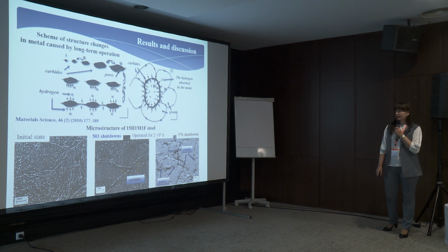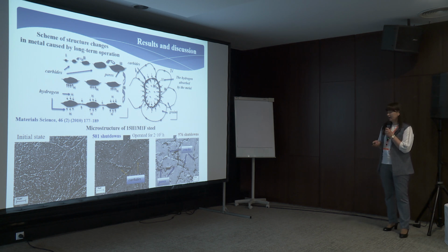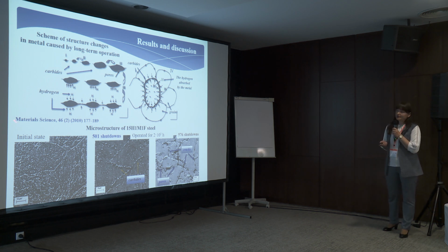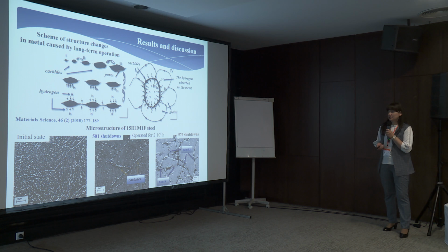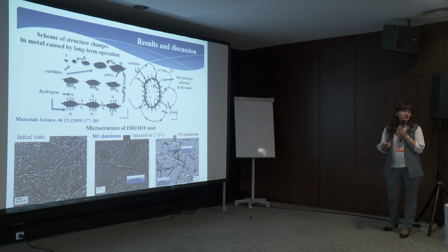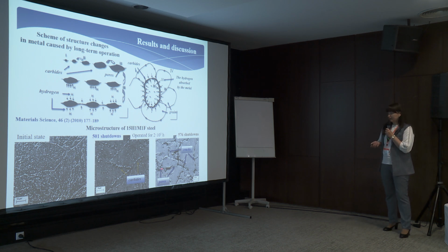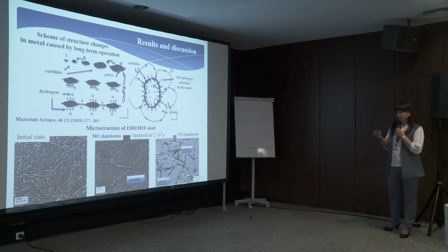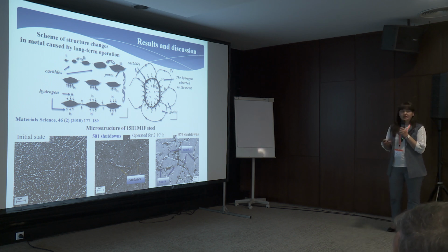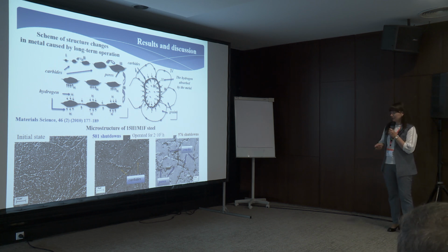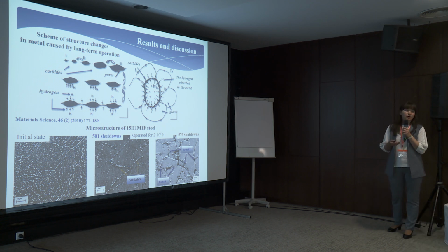Grain size and carbide size in the structure are quantitative structural indicators that determine its mechanical properties. It was shown in our previous research that high temperature operation results in redistribution of carbon and alloying elements in the steel with precipitation and coagulation of carbides along the grain boundaries. Coarse carbides at the grain boundaries have weak cohesion with the matrix, which makes easier their decohesion and formation of pores around them. This reduces cohesion of adjacent grain boundaries. Further formation of a system of microcracks significantly affects the strength of materials.